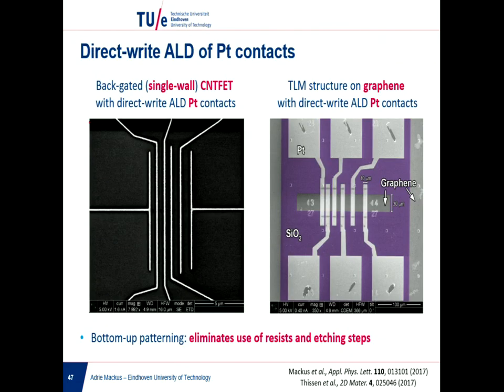Yeah, so this example, I have to remember this. I think this is about between 50 and 100 nanometer in width. And in principle, with the E-beam, you should be able to go to like 10 nanometers. We also did some demonstrations of that, but with the E-beam, it's also challenging to make two contacts next to each other so that they don't influence each other. A related question might be, if you do deposition, do you only grow in the vertical direction or also in the lateral? That's the typical question with area-selective ALD. I'll come back to that at the end. That's one of the challenges that we're currently facing.